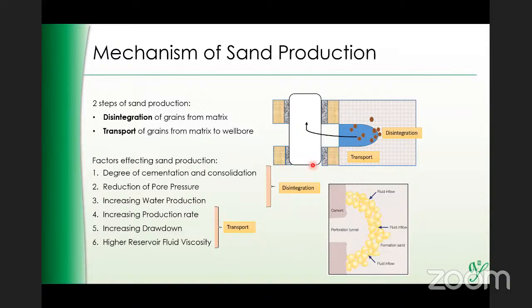So increasing production rate. As you increase the drawdown, you will see that the forces acting on the particles are greater and greater. And because of this, the sand starts moving in. And as you increase drawdown, you have the same effect. It just keeps moving in. And particularly when you increase the drawdown and your reservoir pressure is dropping, overall, the stresses on the rock become greater.